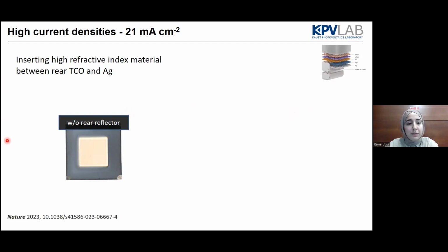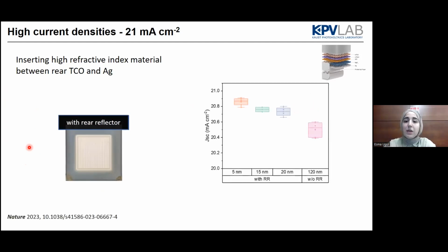basically what we did, this is the regular device at the backside of the device, and this is with the rear reflector. For that one, we are putting a high refractive index material between the silver and the TCO at the back that we are using. And then we also tune its thickness to get rid of the parasitic absorptions, let's say. And you can see that we can get up to 20.9, close to 21 milliamps per centimeter square with the optimized devices. Before doing this, for sure, we did some optical analysis, and then with